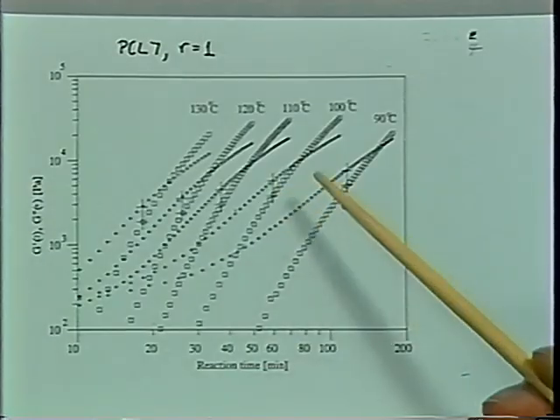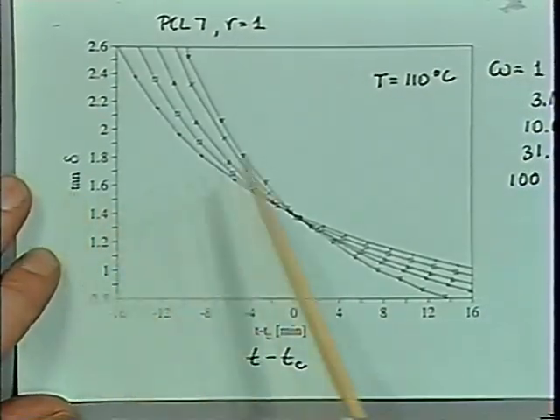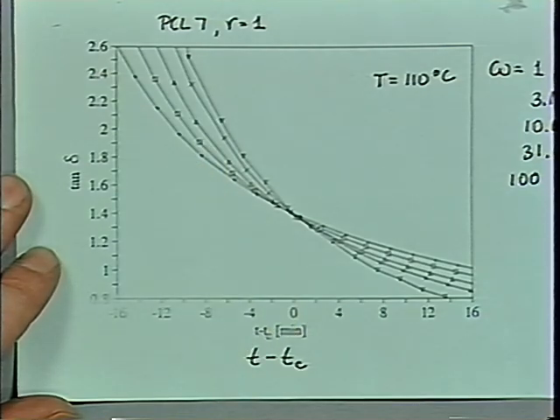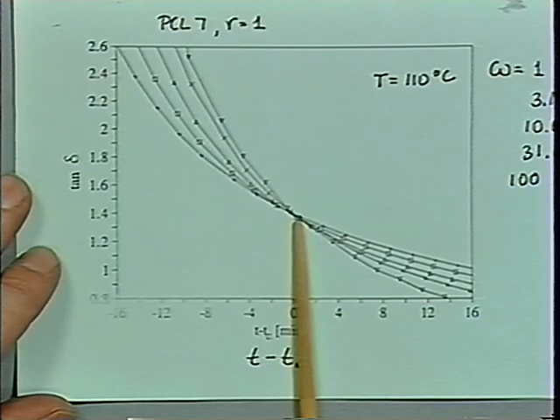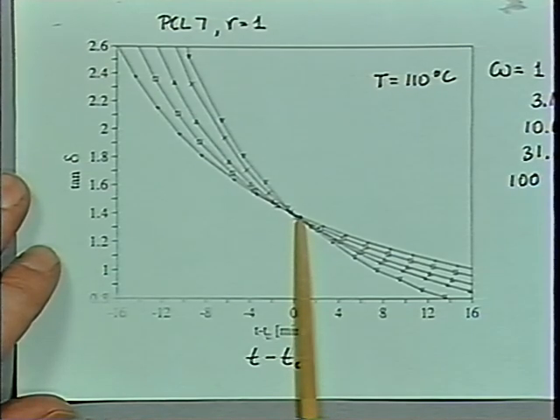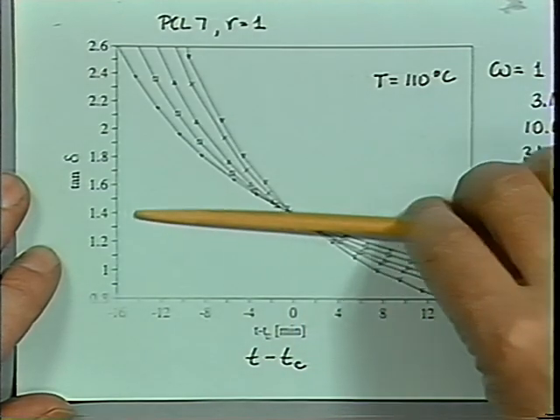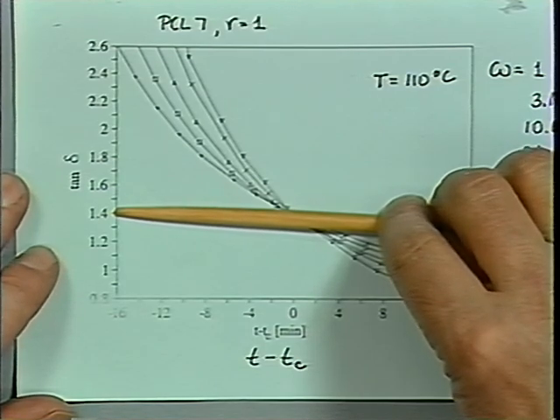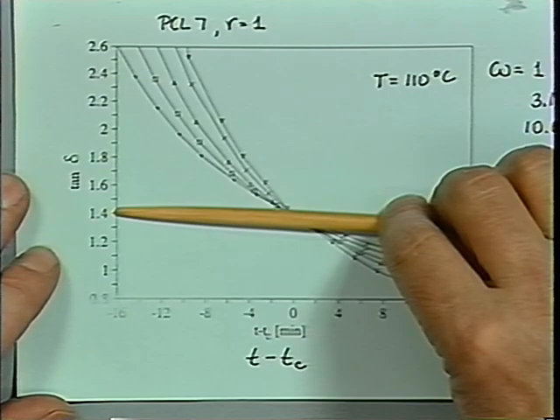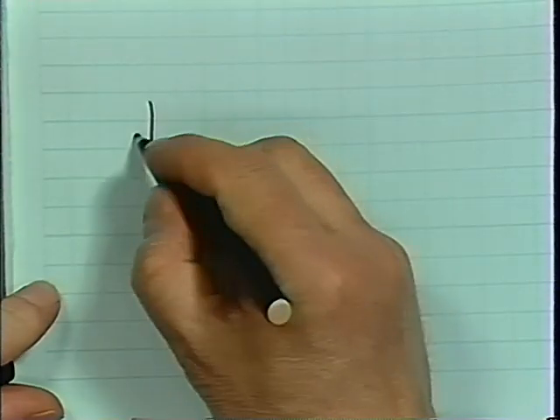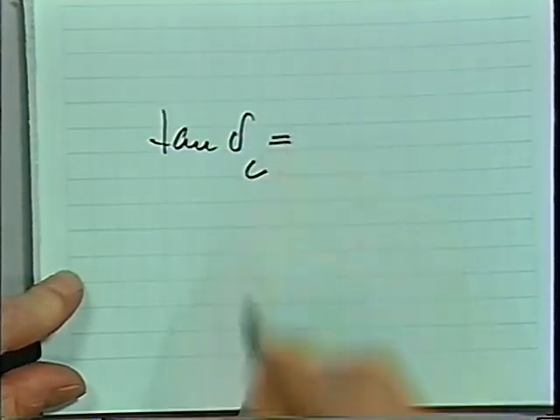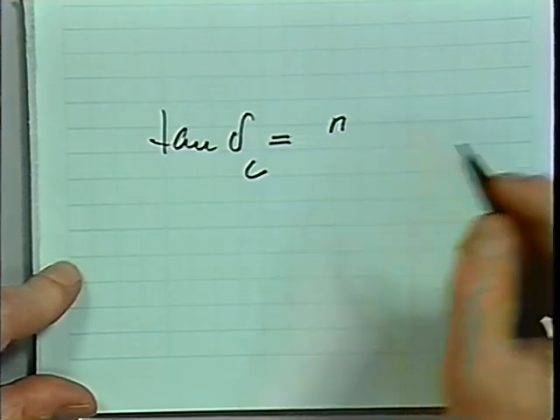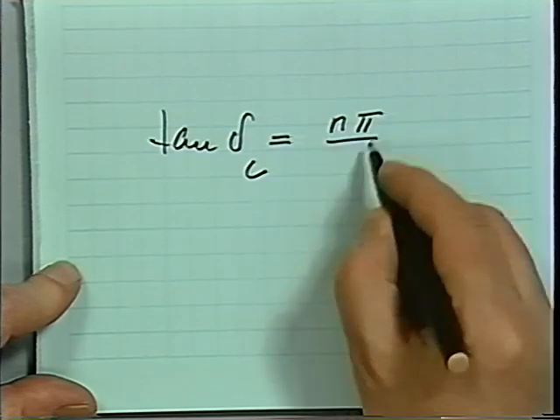He took the curve for the sample reacted at 110 degrees C. There, the reaction was sufficiently slow that he could measure tan delta at a set of different frequencies and plot the evolution of those, and then you can see the gel point is occurring at this time, right? At this time. But he also took a second set of information. He said it's occurring at a certain value of tan delta. Forgot what this value was, but there, for his sample, a certain value of tan delta gives the gel point. And remember the relation that tan delta at the critical point, at the gel point, is given by n, what was it? n pi over 2. Yes, n pi over 2, right?